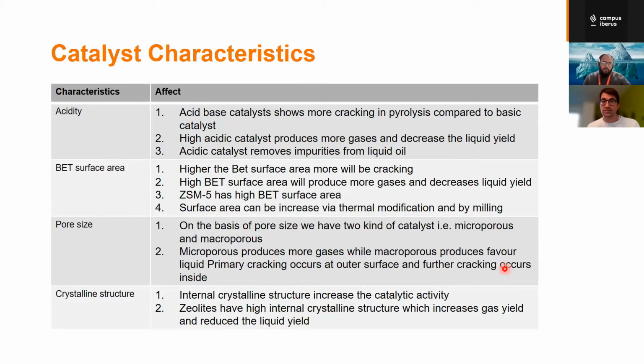And if I talk about the surface area, the simple rule is you have more surface area, you have more cracking. But at the same time, you have more gases, and then you have a decrease in the liquid yield. So there is a compromise where you have to adjust. For instance, zeolites have high surface area, and you can modify the surface area by thermal modification or by milling.